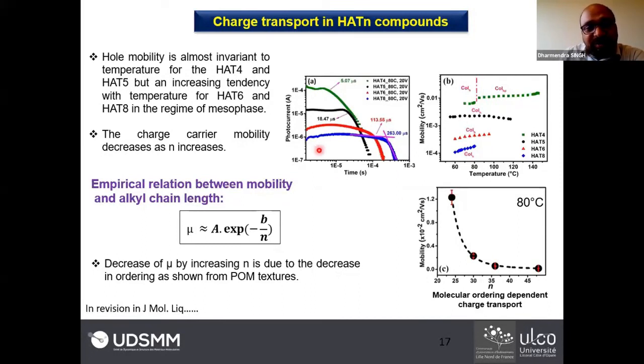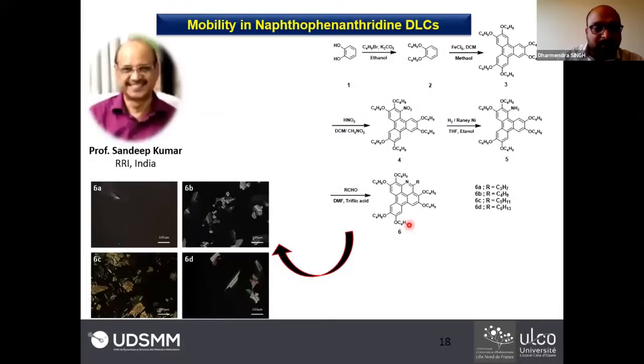We have realized one more thing: as we increase the alkyl chain length connected to the central core of the triphenylene, the mobility also reduces, and it follows an empirical relation like this, which is mentioned here. Basically only the core participates in the charge transportation, but the alkyl chains provide a platform for the charge carriers, whether the path will be convenient or there will be any hindrance. So as we increase the alkyl chain length, they create more hindrance in the charge propagation, and that's why the charge carrier mobility decreases with respect to the length of the alkyl chain. These results are in revision with the Journal of Molecular Liquids.